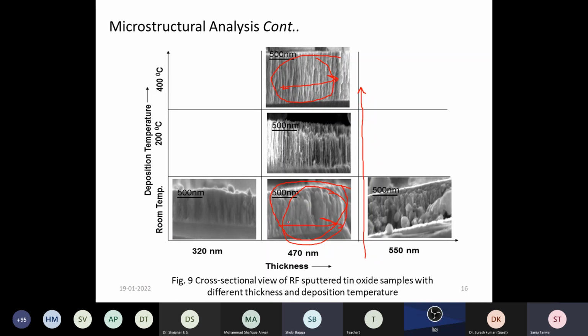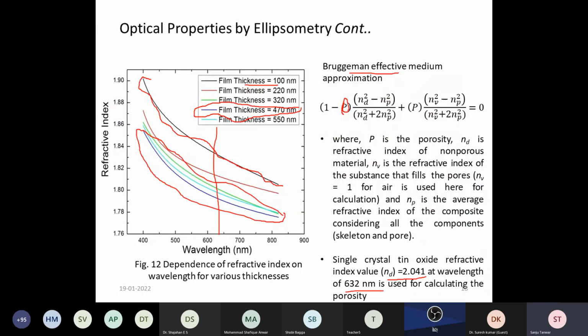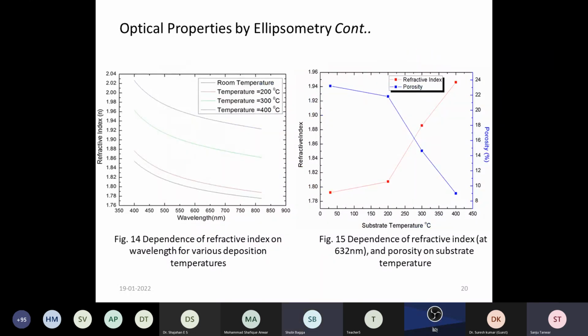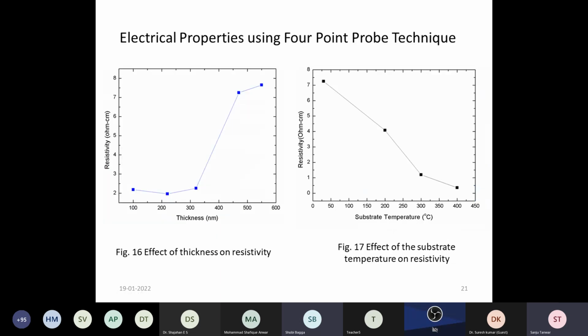These cross-sectional SEM images indicate that it has more pores as compared to the film deposited at 400 degrees centigrade. Second, we have again done this for films deposited at different substrate temperatures, from room temperature. Here we can see the film deposited at the higher temperature, 400 degrees, gives the highest refractive index. Similarly, we have converted it into porosity. The film deposited at 400 degrees centigrade has the lowest porosity and the highest refractive index. Because density is increasing, obviously refractive index will increase and porosity will decrease.